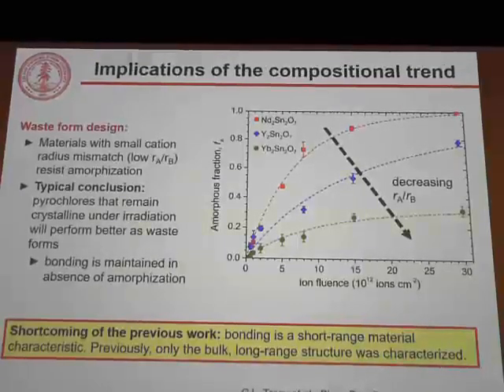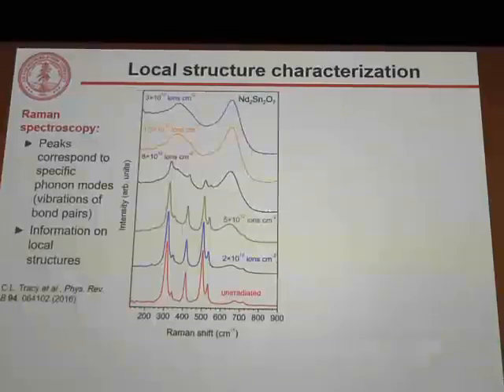So what I did is characterize the local structure of these pyrochlore materials before and after irradiation, first using Raman spectroscopy. Now, in this technique, we get peaks that correspond to phonon vibrations, so vibration of bond pairs, which really tells us about the local bonding and immobilization properties of these pyrochlores. So I show here for neodymium stannate what this looks like, how the Raman spectra evolved as a function of irradiation. And you see the initial spectrum is clearly changed. New peaks arise. Those peaks we have initially are attenuated.